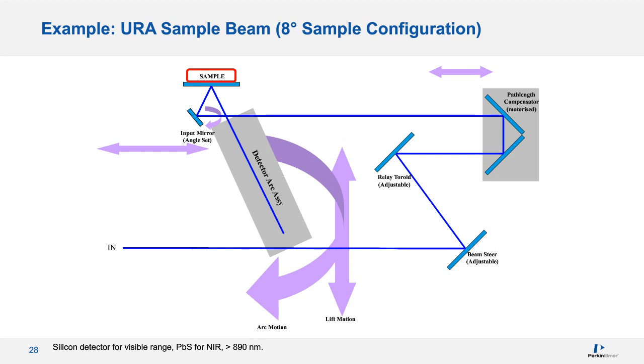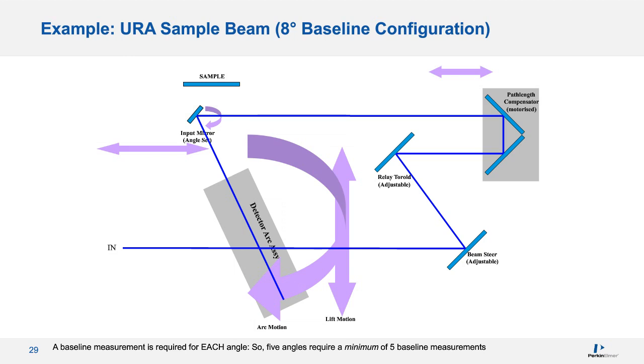This previous background measurement is schematically shown here. If you compare this to the previous slide, you will see that the input mirror just below the sample has rotated down, and the detector assembly has moved in such a way that the total path length of the sample beam has not changed. In addition, the angle by which the detector assembly is held in place is the same as before. So this is an equivalent measurement, but with no sample introduced into the beam path. As such, we can now compare the two measurements as defined by those two slides. The difference between the two is simply the reflectance of the sample. Thus, we have designed a system that can perform automated, absolute specular reflectance measurements.